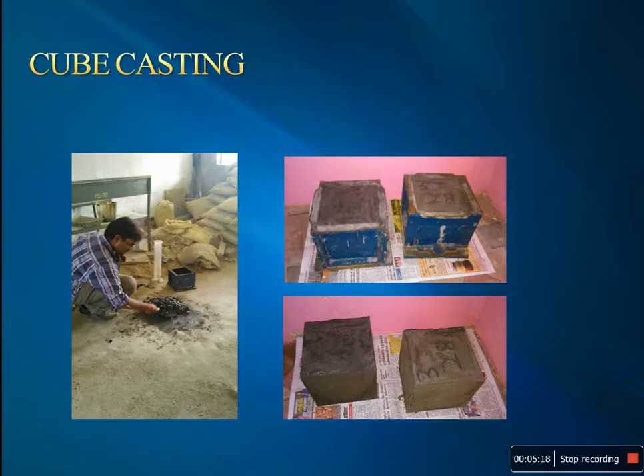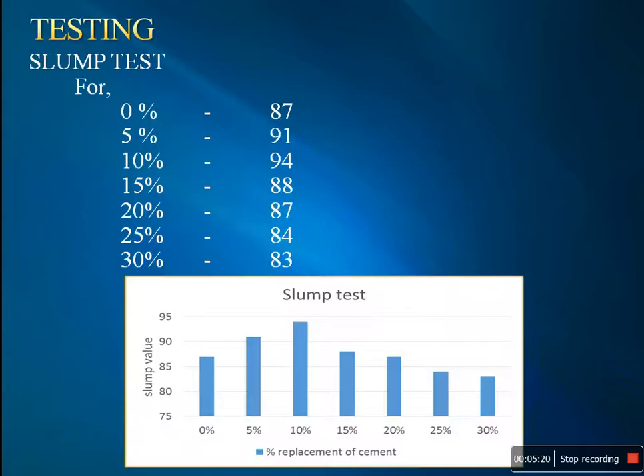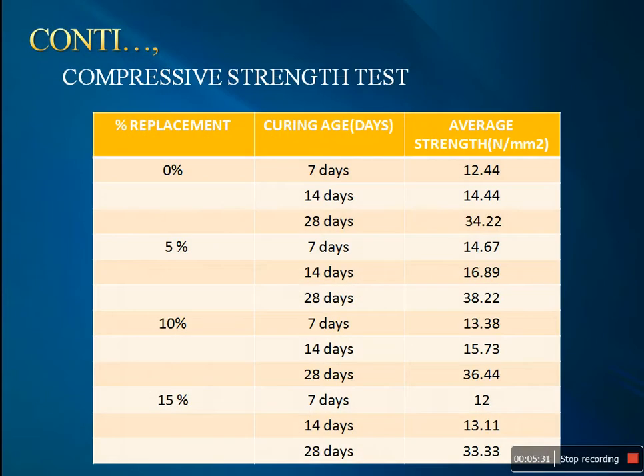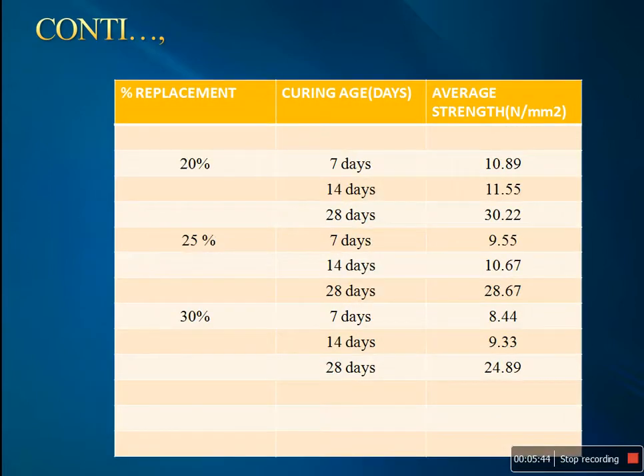My pictures for cube casting, my curing process, my result of some tests. In this test, as you see, from 5% and 10% there is increase in strength. My compressive strength result: from this result, I obtained that 5% and 10% replacement of cement by ESP and CSA will increase the strength of the concrete. My final report says that 30% replacement gives the most decreased value of concrete strength.